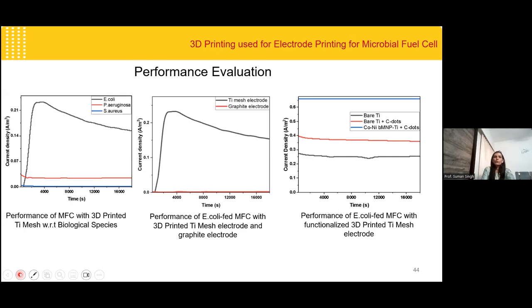our attempt was to increase the current generation. So again, we functionalized these electrodes with carbon dots and bimetallic composites, and we studied their response. The combination of bimetallic nanoparticles, carbon dots, and titanium mesh electrode resulted in a better response. Here, carbon dots were used as an electron mediator in the electrolyte, and cobalt, nickel bimetallic nanoparticles were used to functionalize the titanium. This has resulted in a great advancement in the current, from approximately 0.23 to 0.65.